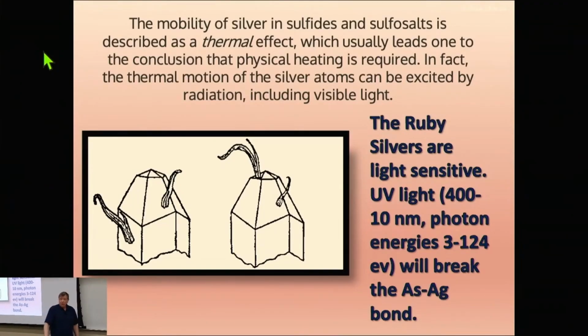So the mobility in sulfides and sulfosalts, including the ruby silvers, is a thermal effect. And it leads to the conclusion that the physical heating is required. But in fact, thermal motion isn't just heating, it's also excited by radiation. And radiation, when I mean this, is a photon, light. So it does exactly the same thing as heating it. So ruby silvers, in particular proustite and pyrargyrite, are very sensitive to ultraviolet light because of the length of the bonds that it's connecting between the silver and the sulfurs.